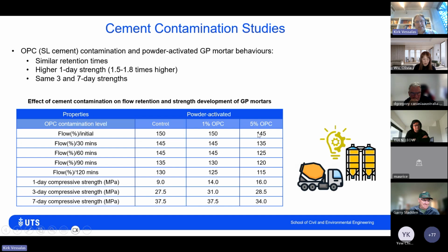We've also done some cement contamination studies because we realize in terms of concrete supply that there may be some cement left over in the silos. And so we've done some studies with 1% contamination and 5% contamination, and the results are pretty impressive. I mean, the flow is still adequate. The retention is there. This is in mortars. Again, we will extend this work to concrete just to verify the performance.